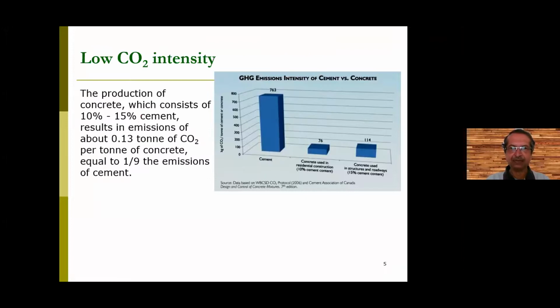No other material can give you this kind of benefit very holistically. For example, if you take the production of concrete, which consists of about 10 to 15% of cement, it results in the emission of about 0.13 ton of carbon dioxide per ton of concrete. Because if you look at 1 ton of cement, right now they say if it is OPC, it is about 763 kgs of equivalent carbon dioxide. So in concrete, we are using only 10 to 15%. So per ton of concrete, we have around 76 to 114 kgs of carbon dioxide emission.